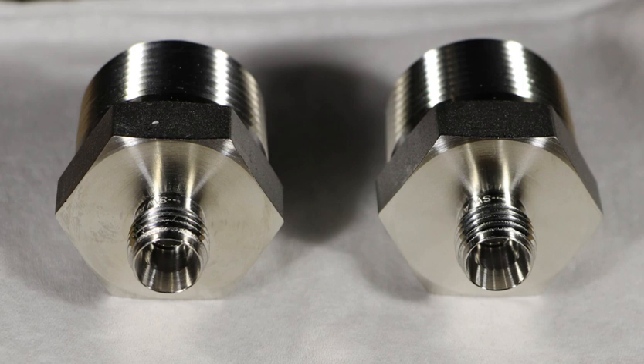The passive surface is validated using humidity, elevated temperature, a rusting agent, salt spray, or some combination of the three. However, proprietary passivation processes exist for martensitic stainless steel, which is difficult to passivate, as microscopic discontinuities can form in the surface of a machined part during passivation in a typical nitric acid bath.